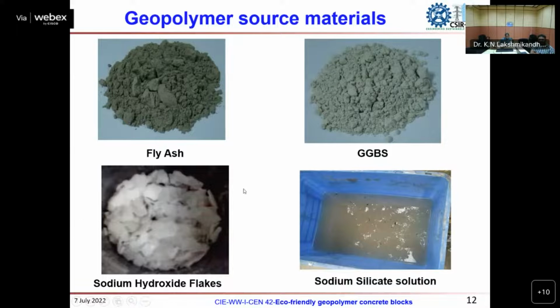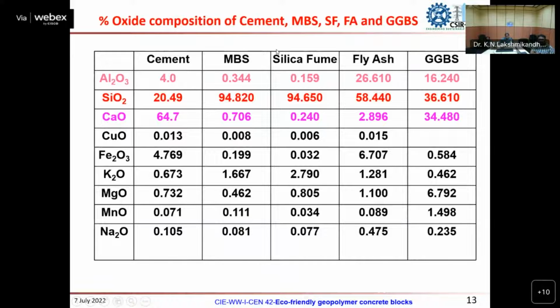And also we may note that sodium hydroxide is available in different forms like flakes, pellets, and also in the lye solution form. And sodium silicate, again, is available in powder as well as in solution form. And when you talk about any source material, proper characterization is required, because we have to see the elemental composition present in the different source and binder materials we are using. Accordingly, because we are looking at the silica and alumina.